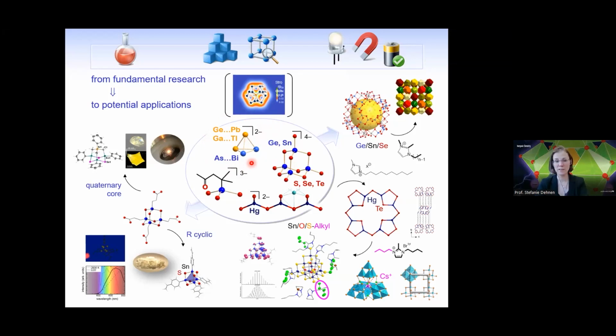And you ask for the room temperature stability. All of the clusters I've shown you during my talk are room temperature stable. Some of them may be a little bit light sensitive, like these tellurium mercurites, as you may guess, but all of them are temperature stable, but all of them are kinetic products in terms of the much more stable binary compounds like salts or metals or the homometallic elements. But this is in terms of oxidation sensitivity. So most of the compounds you're producing are air sensitive, but thermally stable.